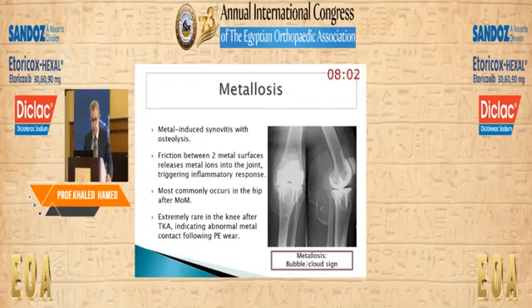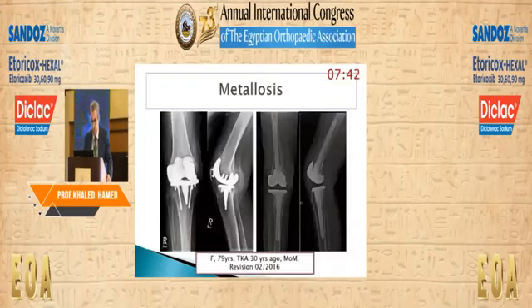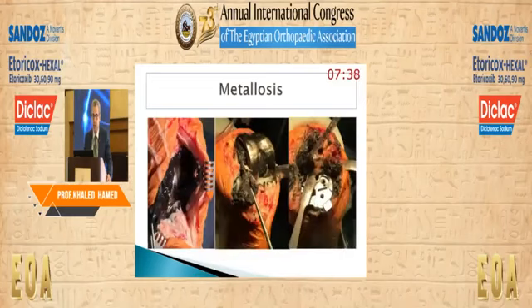rare in knee arthroplasty. It is more common in hip arthroplasty with metal on metal, but I was able to revise 3 cases in Germany with this metal on metal contact because of highly destroyed polyethylene, even with a fracture of the tibial tray. You can see here this bubble sign or cloud sign with metal debris. So this was the revision done for these cases, or one of these cases. And intraoperatively, you can see with metallosis, severe soft tissue destruction.